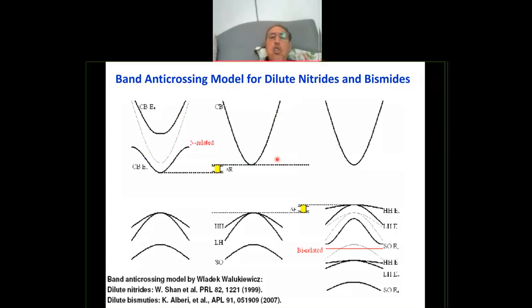So here I just show you in terms of theory what does happen. So this is the conduction band of gallium arsenide. So this is the conduction band, this is the valence band, and this is the energy gap. So when you add nitrogen, what it does is it affects the conduction band. So the conduction band splits. One of them goes down, one goes up, and that's how we reduce the band gap. It doesn't affect the valence band.